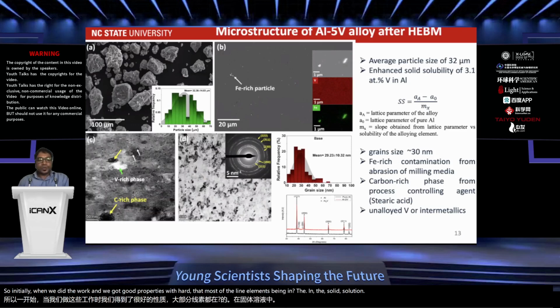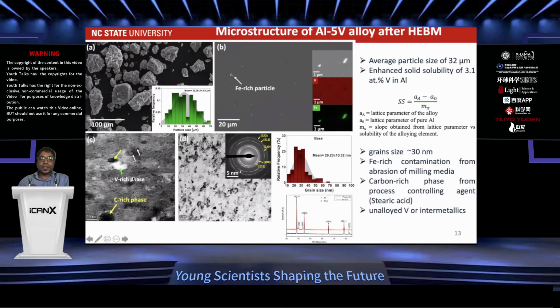But now, once we look at the TEM, we see that there's of course lots of, say, this is one example for aluminum vanadium material. So lots of vanadium is in the solid solution, but we also see a lot of other phases. We see lots of heterogeneities in the microstructure. So we characterized that pretty well.